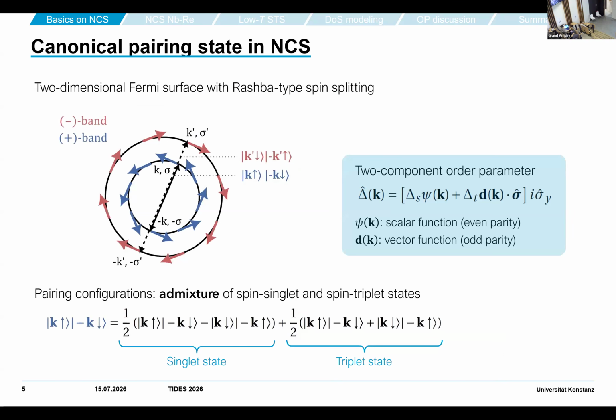How does it work in more detail? The canonical pairing symmetry in a non-centrosymmetric superconductor is that one has this spin-split Fermi surface which is split, and if you go through the math with the outline I gave before, one always has a two-component order parameter that has an even parity scalar component and an odd parity vector function. If you project this on the spin space, you will see that you have contributions of both singlet and triplet components. This is the general symmetry consequence of this symmetry breaking.